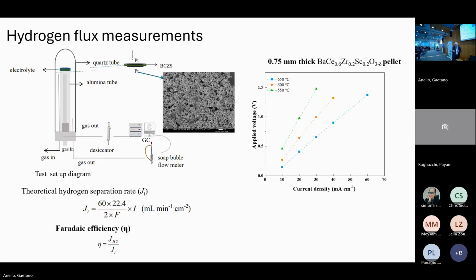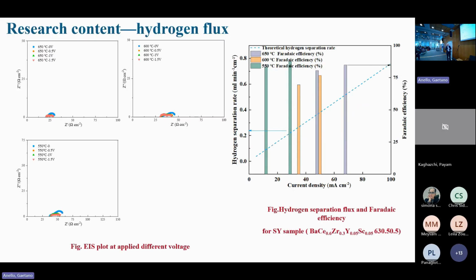Then transport number is an indicator. It's difficult to really look at a full cell. So then we're doing measurement of hydrogen transport directly. So measuring the hydrogen produced, because that's the best way to look at that, and getting the Faraday efficiency from that. Here we have the results. Again, you're getting about 80% efficiency. It's higher at lower temperatures, you're getting 90% at the lower temperature of 550.